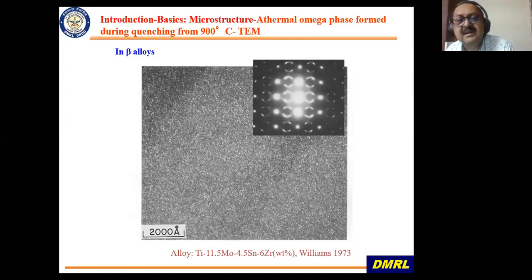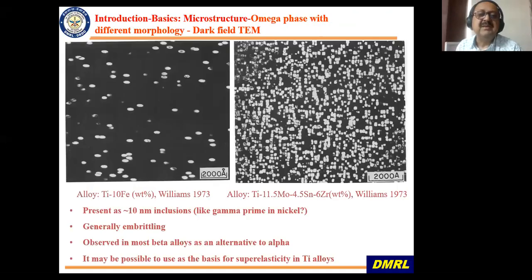It will result in embrittling the alloy, and that is the reason again why beta alloys are slightly difficult to weld also, because of this embrittlement effect which is there. So you have to take care somehow. Similarly, there are different other morphologies of omega phase, it can occur in cuboidal shape or ellipsoidal shape. Again, depends on the misfit which is there due to the alloying element. But these phases you will not be able to see even under SEM. So you will not see them, although they will affect your mechanical properties. So in case of beta alloys, you need to be careful.